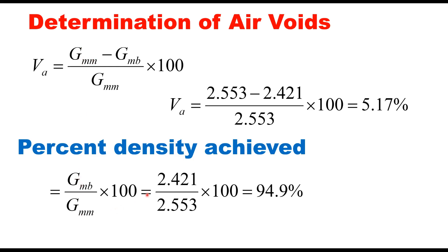The design density, the theoretical maximum density is 2.553. The obtained density in field is 2.421, and therefore you can say that 94.9 percent of the density was achieved in field.